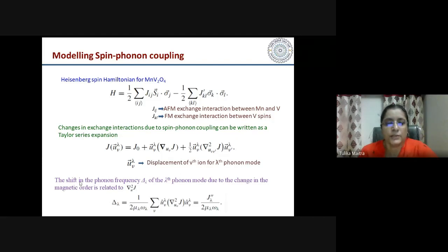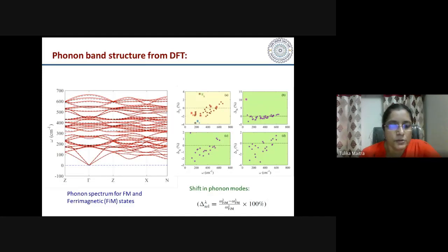So the shift in the phonon frequency can then be related to the second order term, and the shift in the frequency can be calculated from density functional theory from the phonon spectrum for different magnetic states. We can calculate the phonon spectrum for different magnetic states, and we can calculate the shift in the frequency at different points in the Brillouin zone.